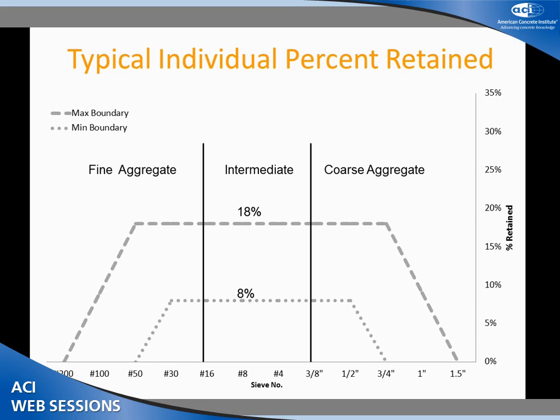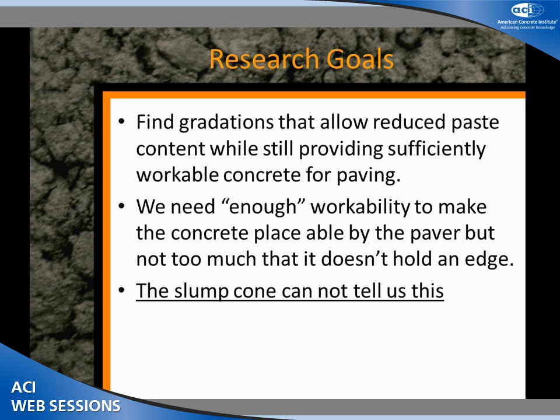The common recommendation is you want to be somewhere between 18 and 8. This is an awesome chart developed by Shilstone, but there is no technical reason for 18 and 8. He actually just pulled it out of the air one day at an ACI meeting when pushed on the chart. People often say you want a haystack-shaped curve, but there is almost no real laboratory data to back this up.